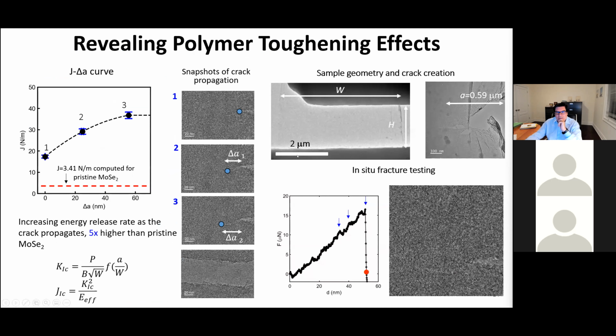So these are some of the measurements. Here is the region of the specimen, it has a certain width and height. We introduce a crack by radiation of the electron beam. And as you see, it's not as perfect as we would like, but you can generate a sharp crack. And then we take a movie, you will see this movie, and we measure load displacement. By analyzing the movie, we can find the position of the crack tip at different instances when these loads drop. And then, using fracture mechanics, compute the initiation toughness as 0 crack advance for the first measurement, and then the toughness as the crack progresses.